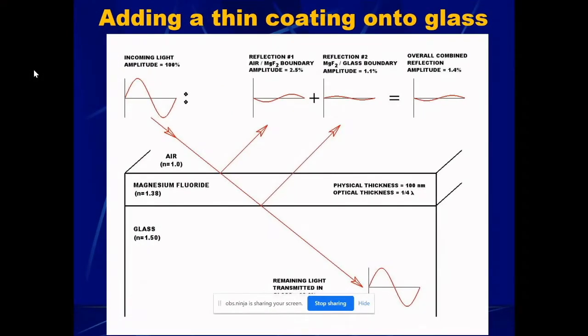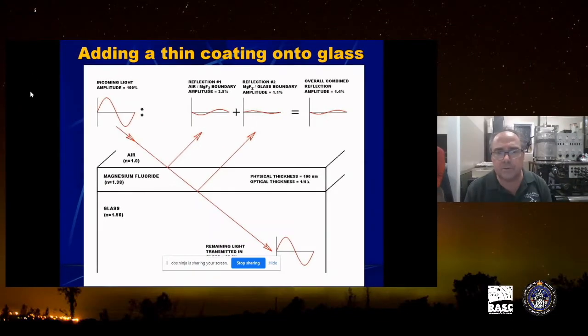Well, what we do is we add a second wave, just like the bulbous bow did, and we use thin film coatings to do this. One of the materials commonly used for lenses is magnesium fluoride. As you can see, it has a slightly lower refractive index than glass does, and that's important because whenever light strikes an index of refraction that's lower than glass, we create a smaller reflection. So as you can see here, the first reflection off the magnesium fluoride boundary is only about 2.5%, compared to bare glass, which was 4%. The rest of the light goes through unabsorbed. But then the light going through the magnesium fluoride boundary now enters into glass, which has a higher index of refraction. So we get another reflection going on here.